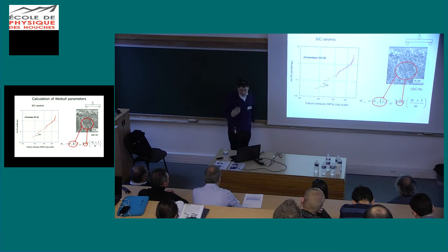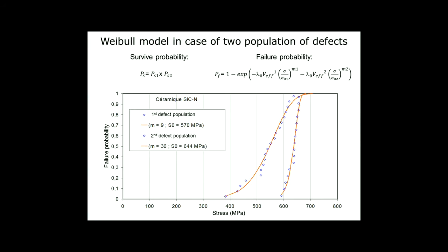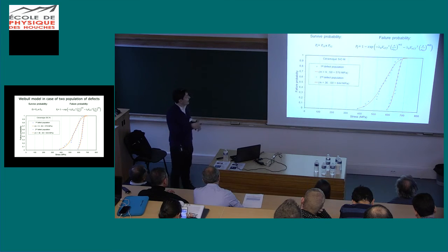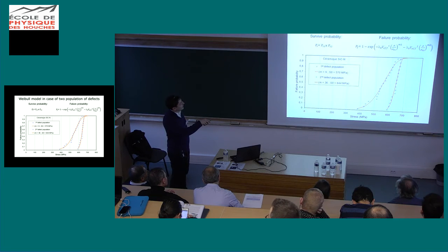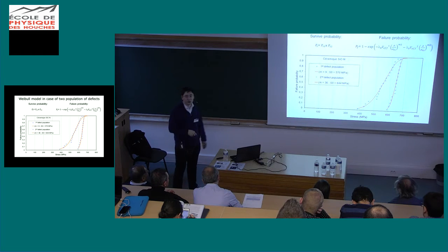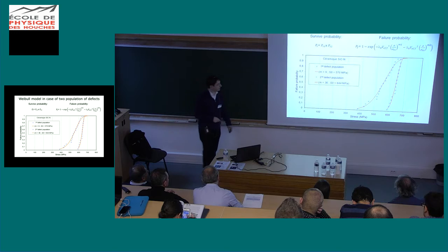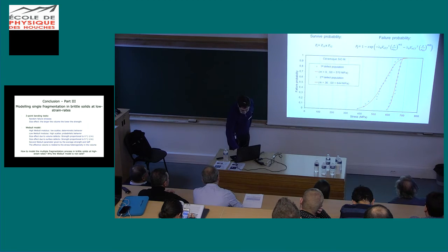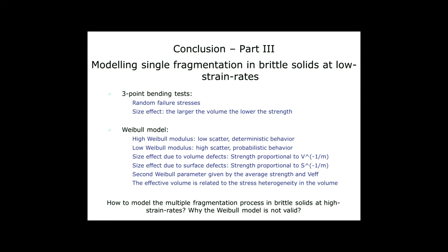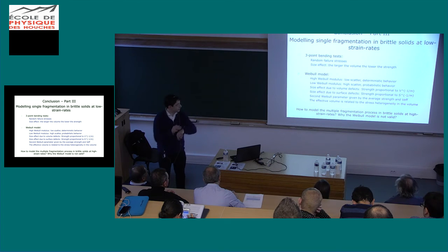That's why it was possible, in fact, to separate both defect populations and now to identify the Weibull parameter related to the first population of defects and to the second population of defects. And you can see here it was m equal 9, and these are the Weibull parameters corresponding to each defect population. So, according to this Weibull approach, I hope I am in time.